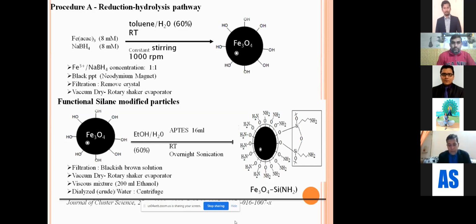We want the nanomaterial in the conductive form. You want the optical property. You want them to be conductive. So we have used toluene, and in the presence of that we were able to form the magnetite. I told you what is magnetite and what is the difference between the magnetite and the superparamagnetic iron oxide nanoparticle.